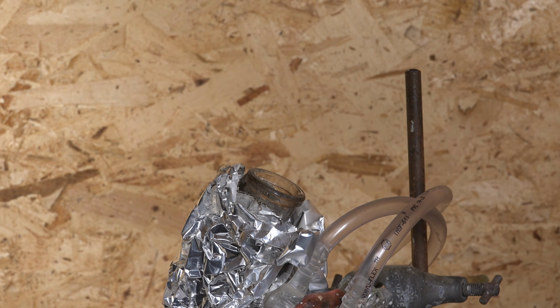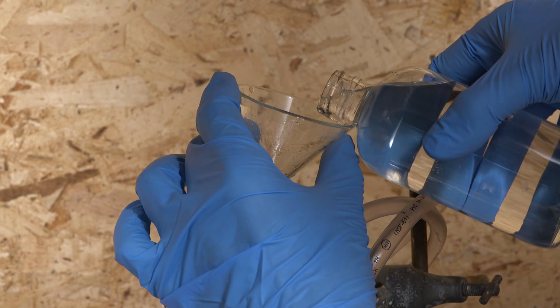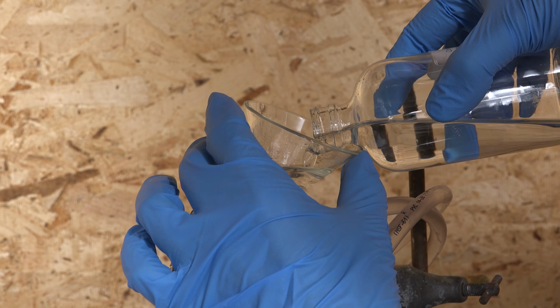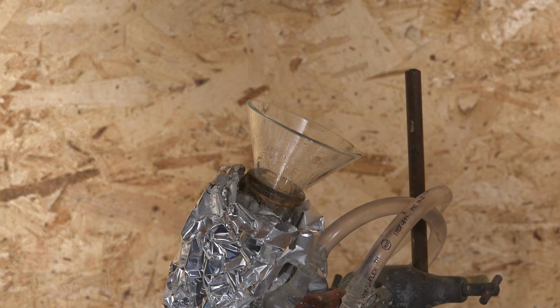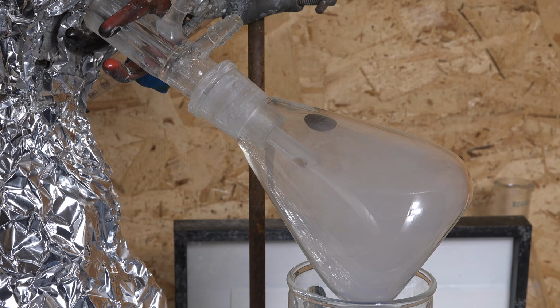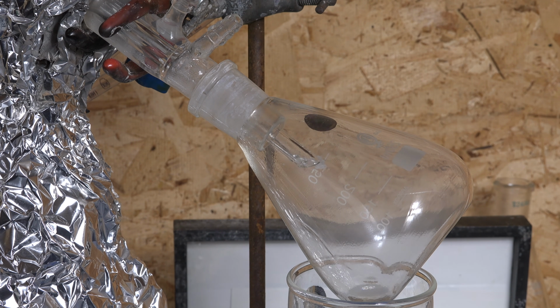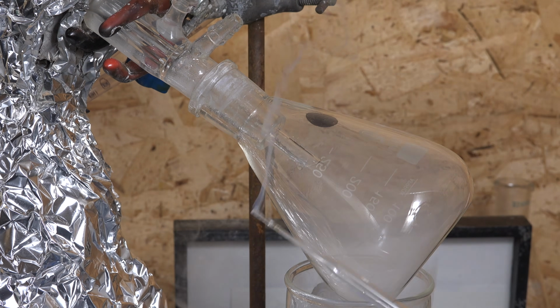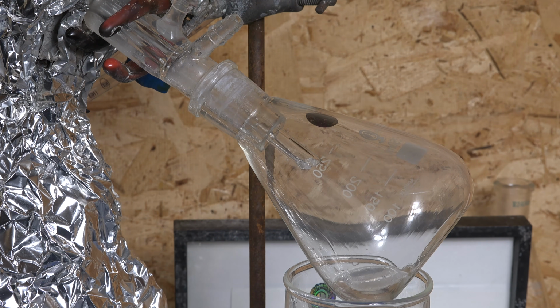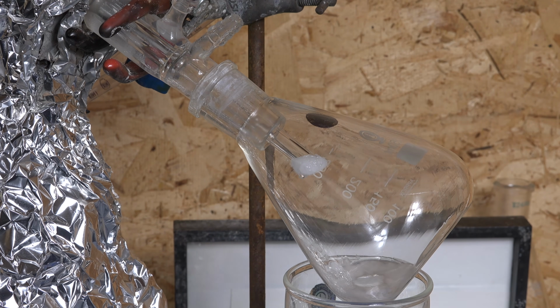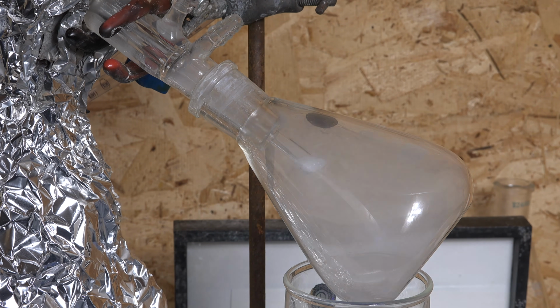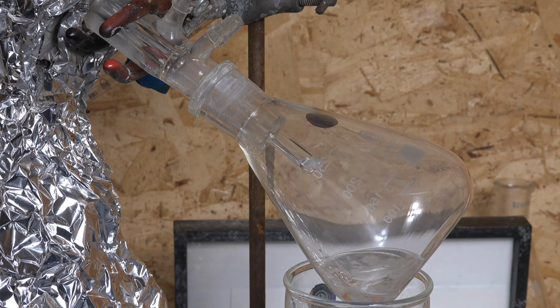Anyway, another test I did was instead of just 200 grams of acid, I used 400 grams. I just wanted to see if there might be an equilibrium effect where adding more acid makes the sodium pyrosulfate react more and release the sulfur trioxide sooner. But instead the yield got reduced, so I think adding more has no effect on the equilibrium. And the reduced yield came from the fact that the extra sulfuric acid also has 2% or so of water, which itself reacts away what meager sulfur trioxide is produced. So that's good to know. Maybe I should go with 100 grams of acid next time and test a small amount, since we're not getting high enough yield anyway to warrant 200 grams of sulfuric acid.